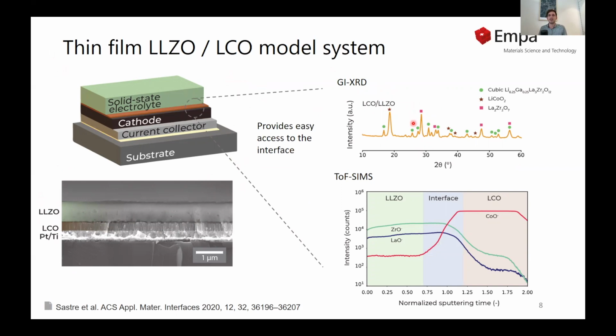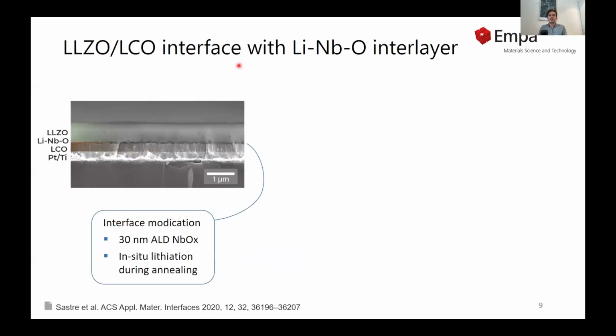the garnet phase. We also looked at the elemental distribution around the interface by time of flight secondary ion mass spectroscopy, TOF-SIMS, and we observed that zirconium and lanthanum are diffusing into the cathode, and cobalt is also diffusing into the solid electrolyte. This model system also allowed us to investigate interface modifications to prevent such an interface degradation process.